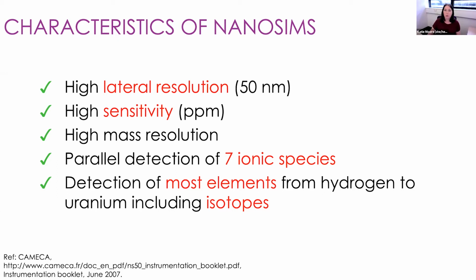So one of the key capabilities of NanoSIMS compared to other SIMS instruments is the fact that it has high lateral resolution. So we can focus that primary ion beam down to 50 nanometers. And this is much higher than you could get with other SIMS instruments. It's also higher than you can get with chemical mapping in the SEM, for example, but not as good as TEM. So it fits somewhere in between.